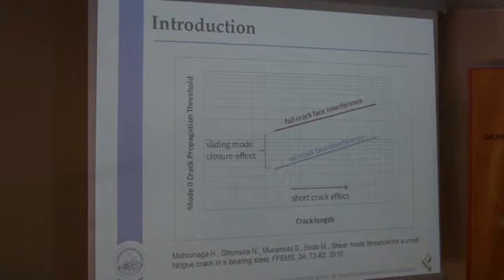Propagation is also strongly affected by crack face interference, which causes the so-called sliding mode or roughness-induced closure effect. This effect is able to increase very significantly the propagation threshold because of the locking effect between asperities of the crack faces. And we remember that the crack propagation threshold is also affected by the short crack effect, that is, the dependence on crack length.